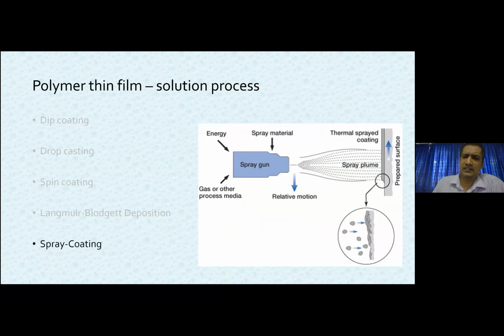The last but not the least method is spray coating, which is an economically scalable method compared to other methods, where you do a spray. Here also the nozzle's diameter, the rate at which you are spraying, the rate at which you are moving from surface 1 to surface 2, and the rate at which the solvent evaporates because of the thermal conditions you keep matter, which was thoroughly discussed in the previous session itself. Spray drying is another technique where you try to get the coating of this solution, especially polymer.